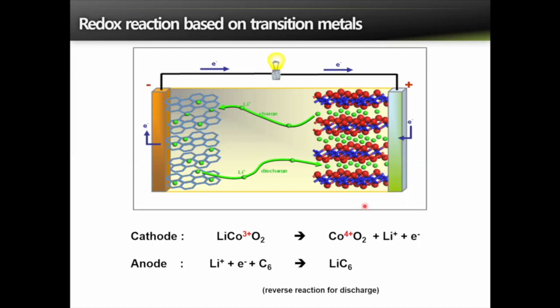Just for recap, lithium-ion batteries are composed of three major components: cathode, anode, and the electrolyte. And with the charge and discharge of the battery, lithium ions are extracted from one electrode and reinserted into the other. And this is the crystal structure of the layered transition metal oxide. One thing that needs to be reminded is that on the cathode side, which requires high redox potential, the redox reaction relies on the oxidation and reduction of the transition metal, which allows electron storage. The transition metal redox exhibits generally high potential and high reversibility. And this is why most of the cathode materials contain transition metals, such as lithium cobalt oxide, NCM, LFP, and LMO, et cetera.